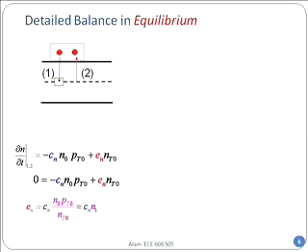In fact, detailed balance is a way in which in any rate equation, this is semiconductor physics, you can take anything. You can take geophysics, you can take astrophysics, anywhere. This notion of detailed balance is so powerful, it will always connect two processes or a couple of processes in equilibrium to each other and thereby reduce the coefficients by a factor of 2. It's a very powerful technique. So one thing you see is that emission is related to the capture coefficient multiplied by a bunch of constants, and we'll think about what those constants are.